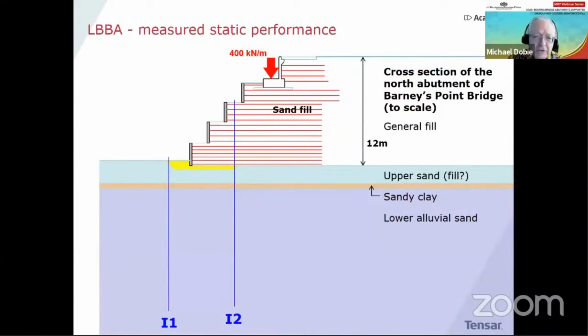So there we have a nice cross-section of the structure. So you can see there the tiered shape, the series of steps that form the facing. Quite a high load. The typical loading from the bridge, for the design anyhow, was in the order of 400 kilonewtons per meter along the abutment. So that's quite a high load. Overall height about 12 meters from the original ground level up to the road. And you can see the position there of I1 and I2. Now, one nice thing about inclinometers is as long as they don't get blocked, or too distorted, they will last for a long time.